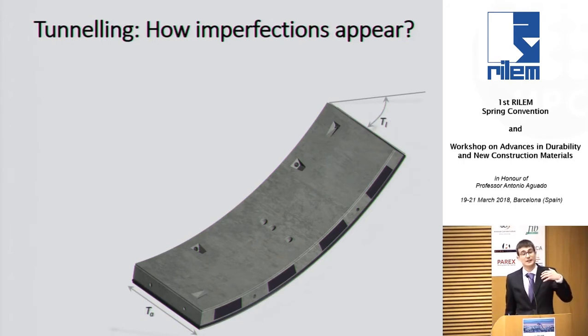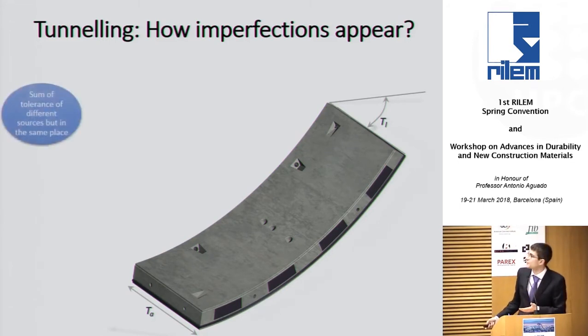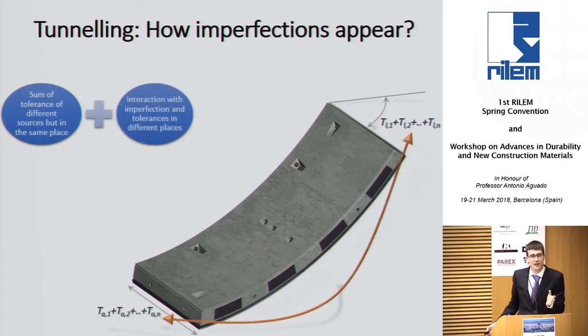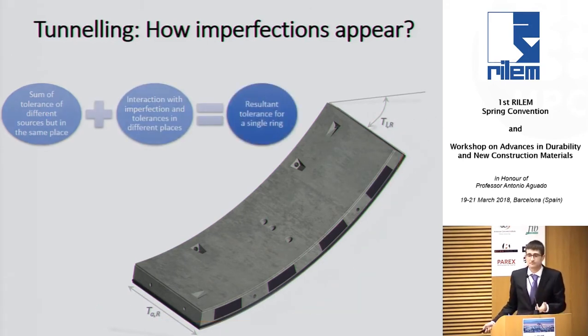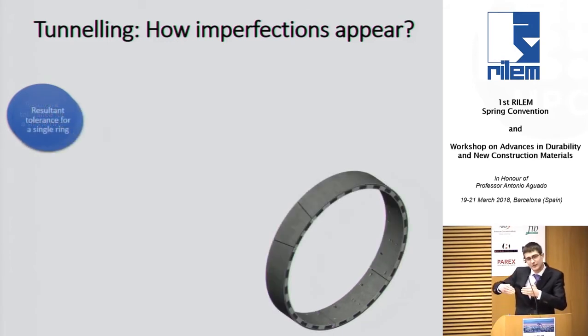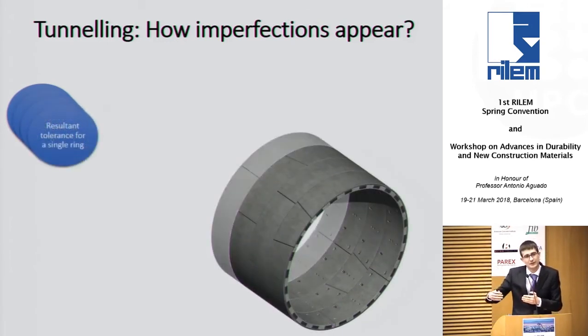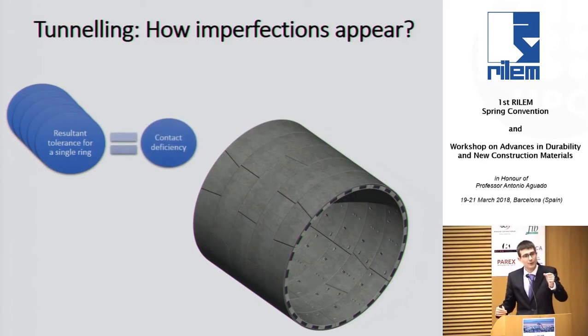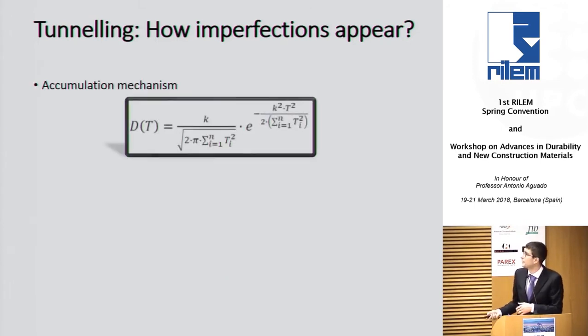And I said before, they come from tolerances, many types of tolerances. It could be differential shrinkage. It could be the tolerance of the molds, the formwork used to produce the segment. So there are many sources of tolerances that are summing together one with the other, and they are giving, when you place one ring after the other, an accumulation process that increases them by a factor that could range between 3 and 4, right? But we had to understand how this increase would happen, right?